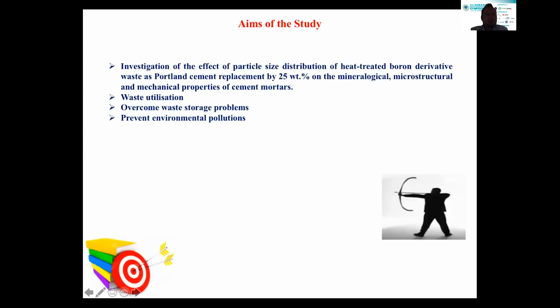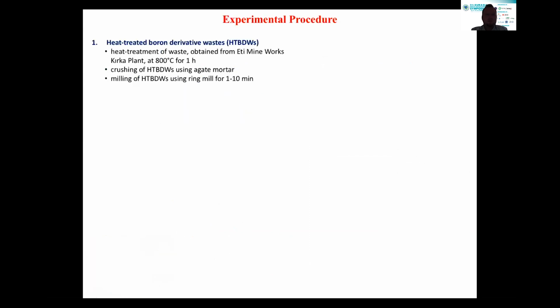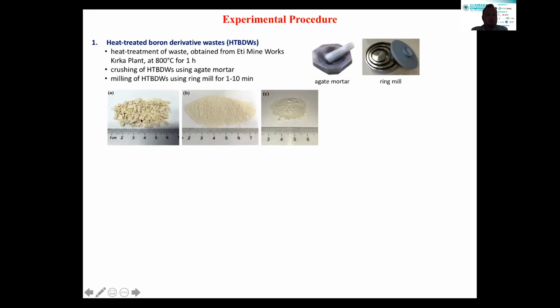So the aim of the study is firstly to investigate the effect of particle size distribution of heat-treated boron derivative waste as a Portland cement replacement by 25 weight percent on the mineralogical, microstructural, and mechanical properties of cement mortars. With the waste utilization, we can overcome the waste storage problems and also prevent environmental pollution. Firstly, we heat-treated the boron derivative waste at 800 centigrade for 1 hour. After that, we crushed and milled the waste powders by using an agate mortar and a ring mill. You can see in the first picture the heat-treated boron derivative waste just obtained by heat treatment, then the second picture shows the crushed powder, and the third one shows the ring-milled powder. So you can see the decrease of the particle size distribution.